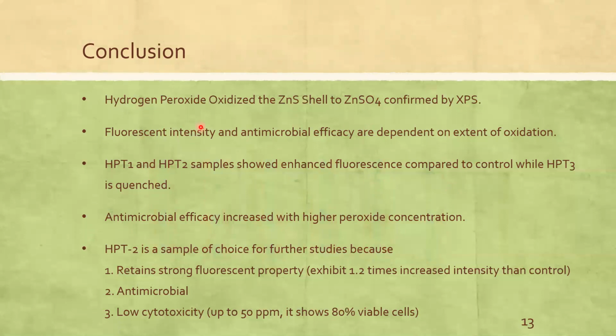In conclusion, hydrogen peroxide oxidized the zinc sulfide shell to zinc sulfate, confirmed by XPS. Fluorescent intensity and antimicrobial efficacy are dependent on the extent of oxidation. HPT1 and HPT2 samples show enhanced fluorescence compared to control, while HPT3 is quenched. Antimicrobial efficacy increased with higher peroxide concentration. HPT2 is the sample of choice for further studies because it retains strong fluorescent property, exhibits 1.2 times increased intensity than control, and is antimicrobial, and also has low cytotoxicity. So up to 50 ppm, it shows 80% viable cells.